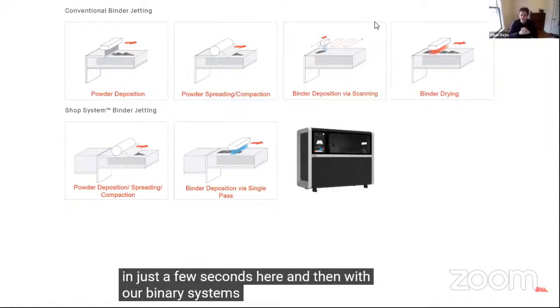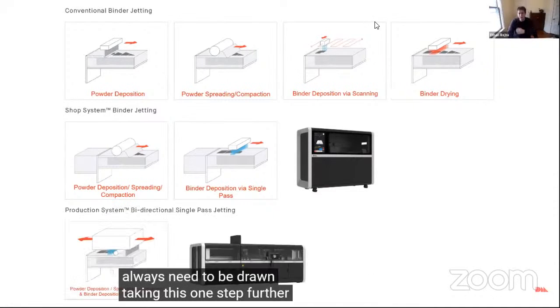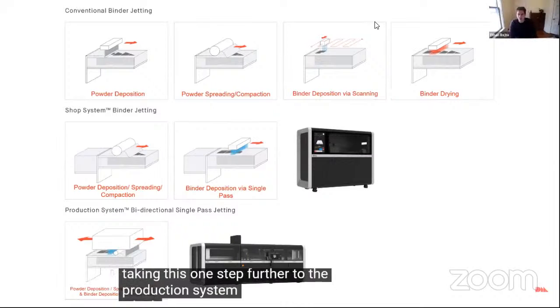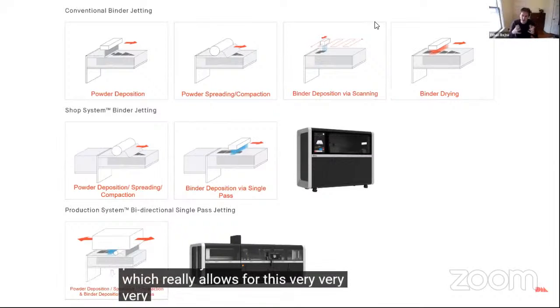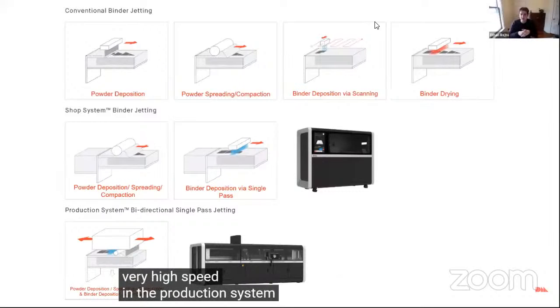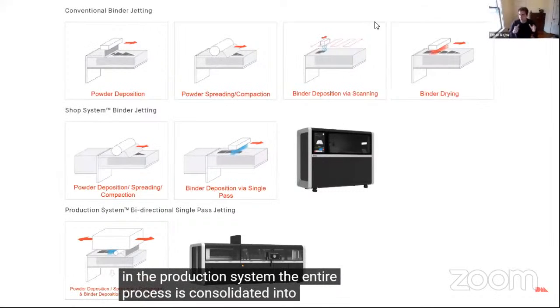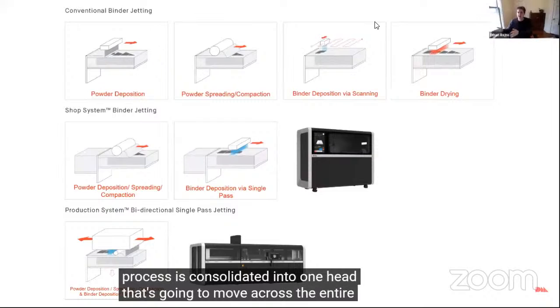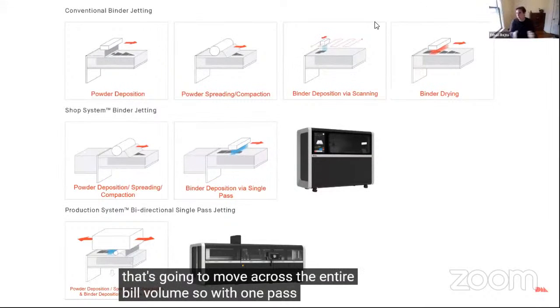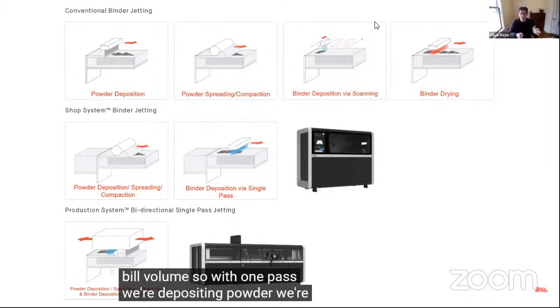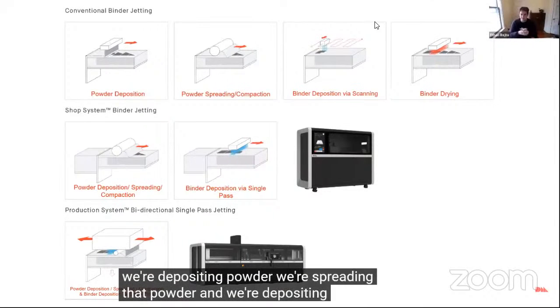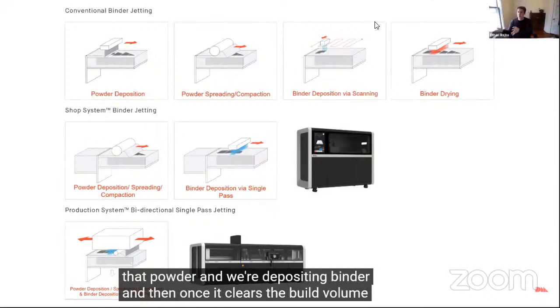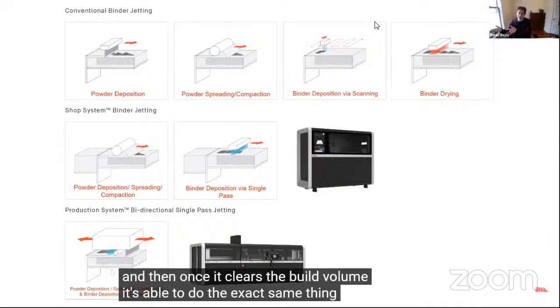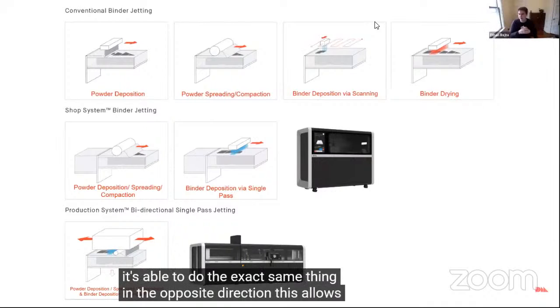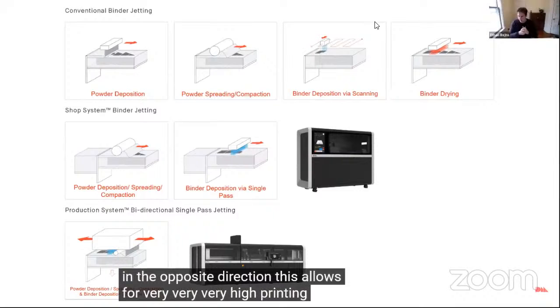And with our binder systems, generally they don't always need to be dried. Taking this one step further to the production system, which really allows for very, very high speed. In the production system, the entire process is consolidated into one head that's going to move across the entire build volume. With one pass, we're depositing powder, we're spreading that powder, and we're depositing binder. Once it clears the build volume, it's able to do the exact same thing in the opposite direction. This allows for very, very high printing speeds.